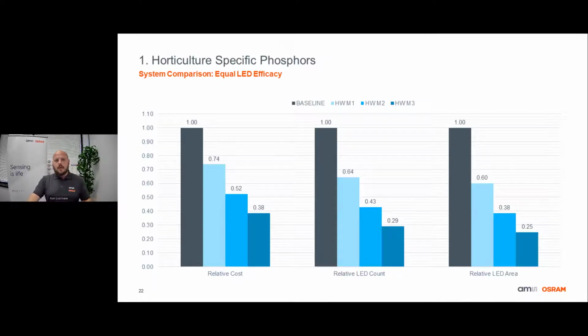Now where Horti white really shines, however, is when we're evaluating the system cost when compared to the baseline solution at equal efficacy. So let's say you're happy with your system efficacy now, but you just want to reduce costs. Well, we were able to reduce LED costs by up to 62%. This is thanks to the greater contribution of the more efficient direct red that then allowed us to drive both the white LED and the red LED harder without negatively impacting efficacy. So this results in an LED count reduction of up to 71%.